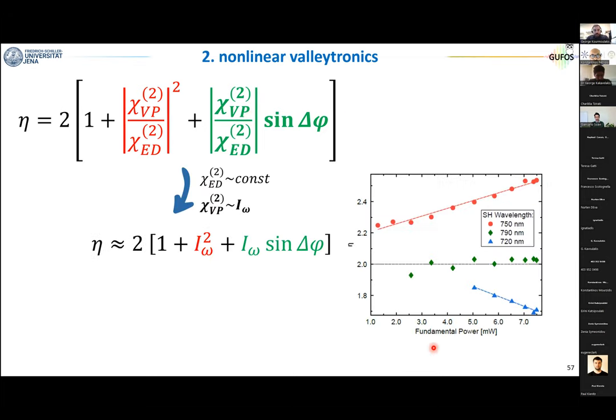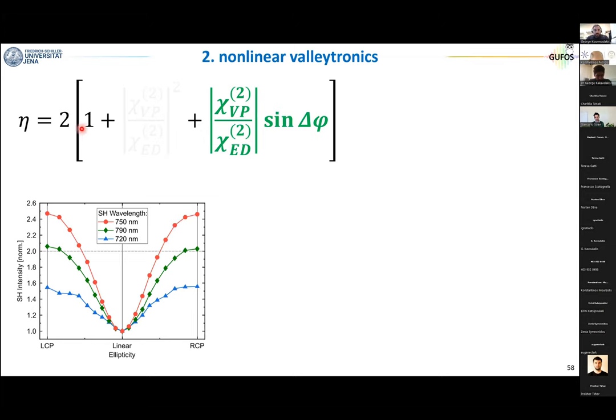Now, if we look at the power dependence of this ratio, so eta is the ratio, 2 means there is no broken time reversal symmetry. Instead, you see that the ratio is different from 2 and scales linearly with the power. Since we know that the valley polarization is linear with the power, this term should go quadratically with the power, this term go linearly. So from this, we can already tell the quadratic term can be neglected. And this is because the valley polarization is smaller than the electric dipole, approximately a factor of 10. So this will be a factor of 100, this will be a factor of 10, this one dominates. But what is very interesting is that the ratio between the two is very different from what you would expect without a broken time reversal symmetry. And it can be both larger than 2 or smaller than 2.